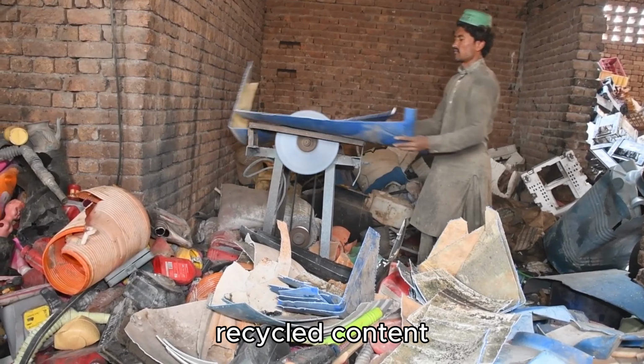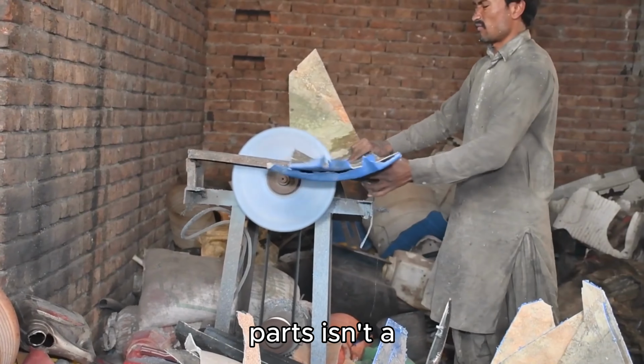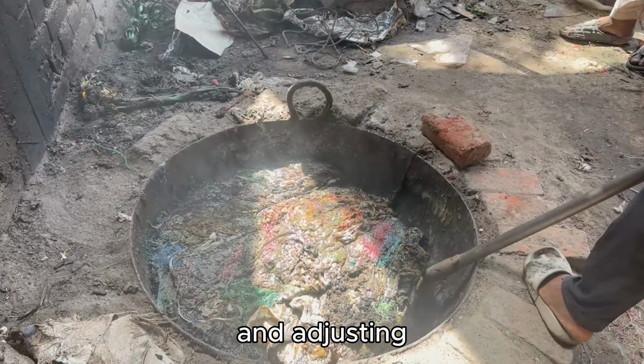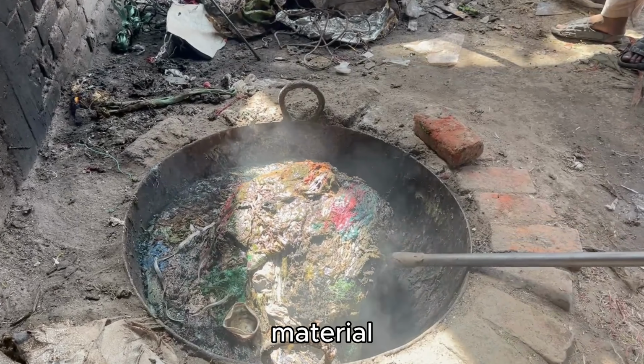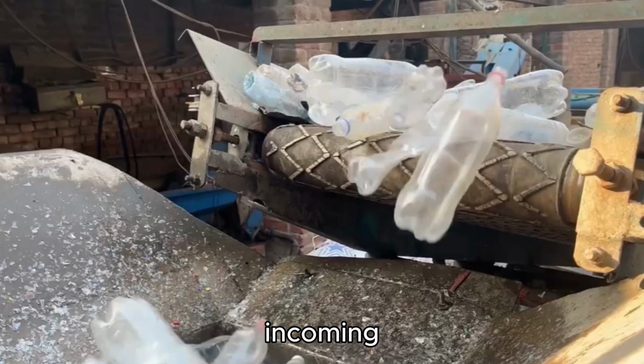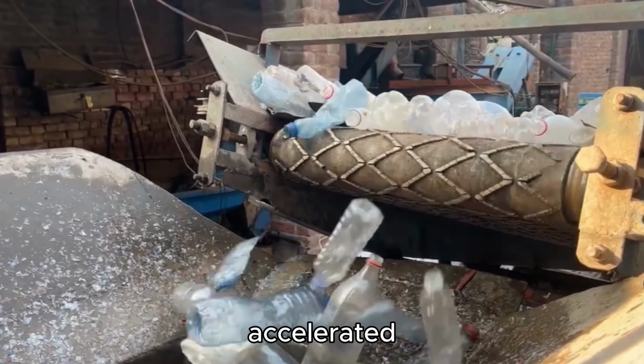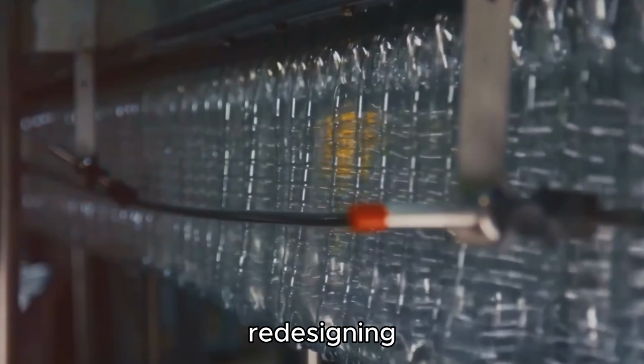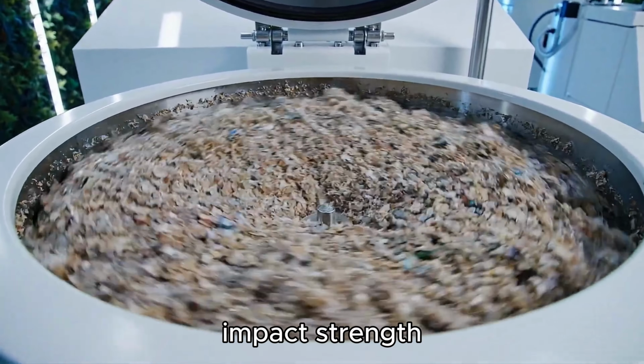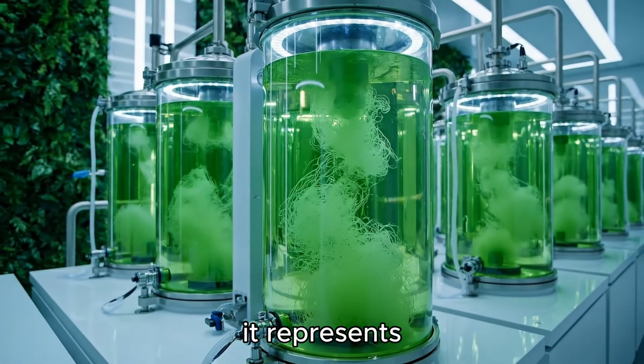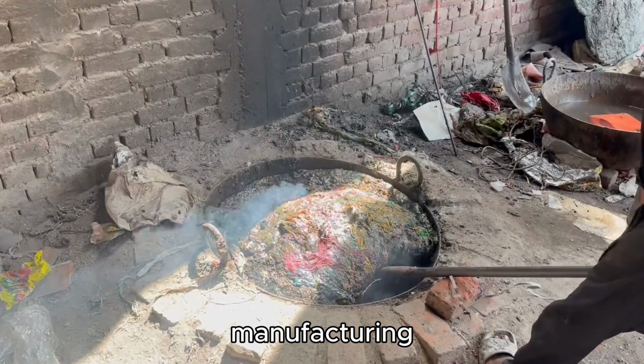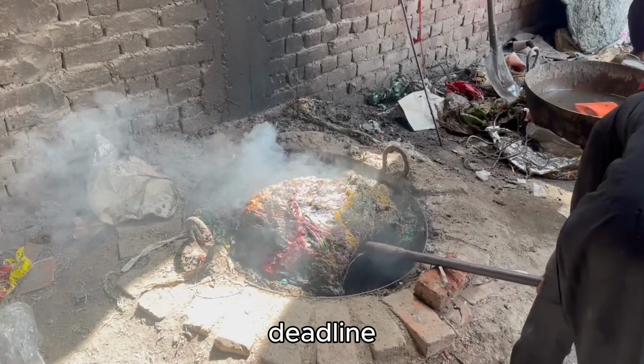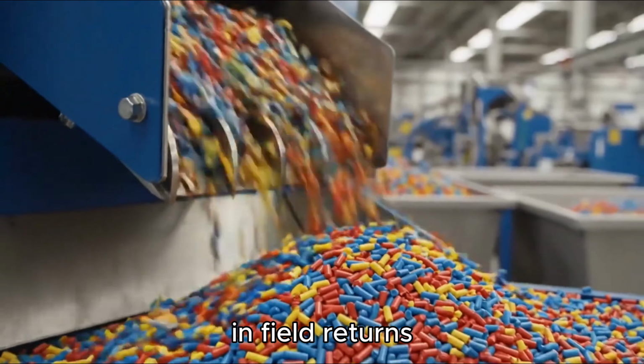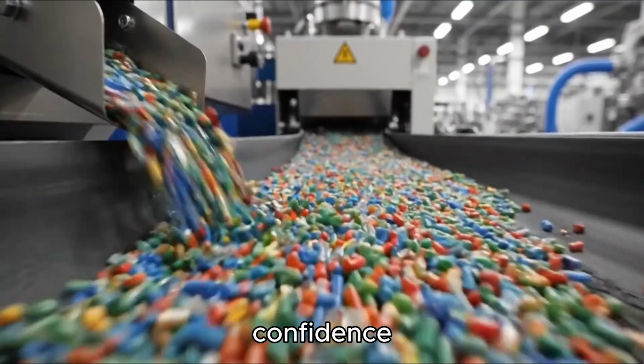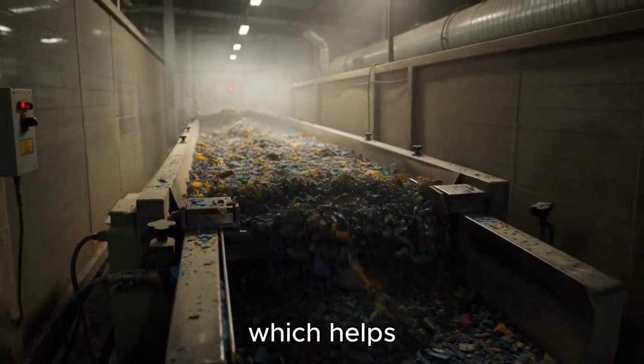Managing post-consumer recycled content in structural or precision parts isn't a matter of swapping in 25% and adjusting one process parameter. Material scientists spend real time characterizing incoming recycled feedstock lot by lot, running accelerated aging tests, and sometimes redesigning wall thicknesses or rib geometries to compensate for reduced impact strength. When that work is done properly, it represents genuine progress towards circular economy manufacturing. When it's rushed to hit a compliance deadline, you get quality problems that end up in field returns, and that erodes consumer confidence in recycled content across the board, which helps nobody.